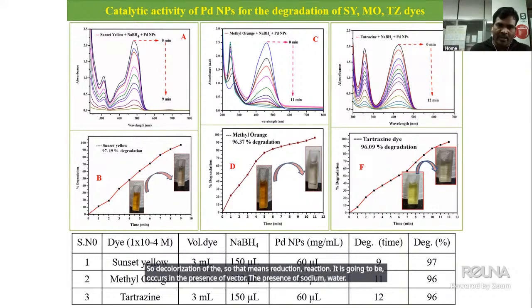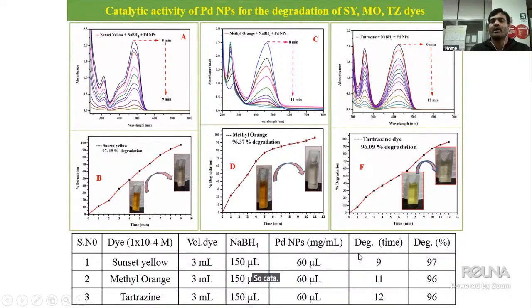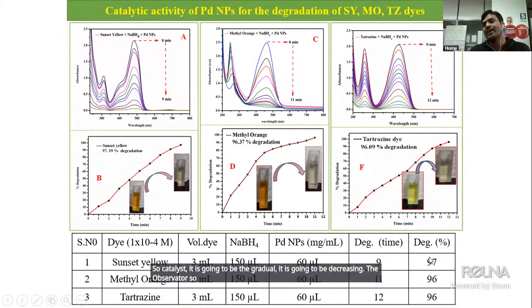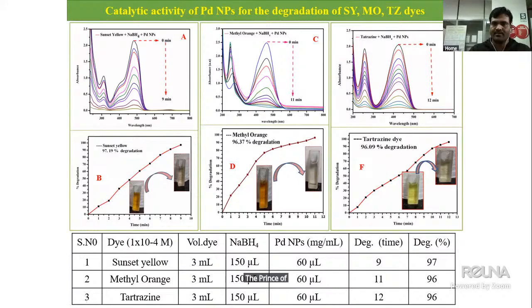Here we use the optimized catalyst. With the optimized sodium borohydride and a sufficient amount of catalyst, the absorbance gradually decreases. A higher percentage of dye degradation is noticed, around 98%, and above 95%, decreased in the presence of catalyst.